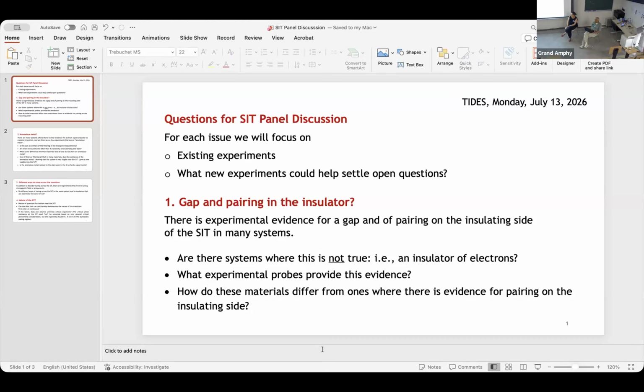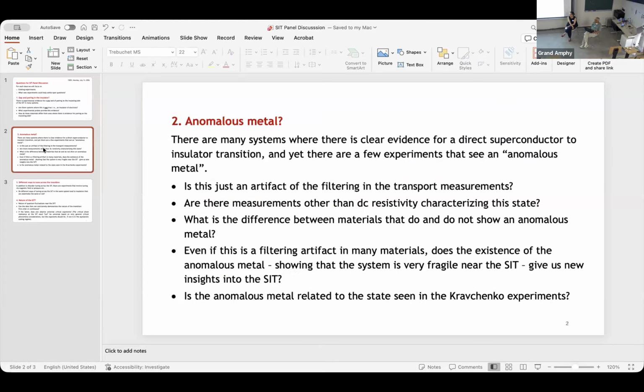I just want to warn that even if the morphology is smooth, you may see different electronic properties. He was asking about grains of superconductors inside the electronic. Yes, of course, that is important to say. Indium oxide, niobium nitride, which is crystalline with still lots of disorder and scattering. In the graphs on the slide, you cannot distinguish amorphous from crystalline. I see. And they are very different from molybdenum germanium.